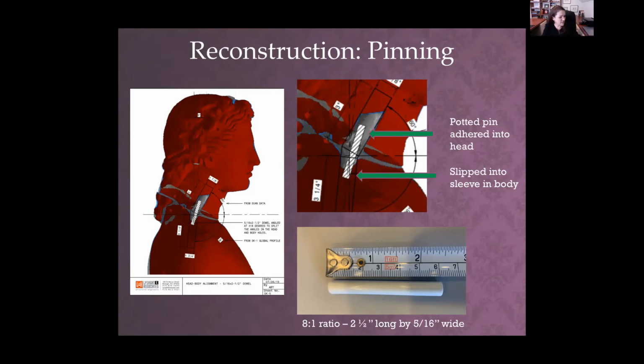One of the steps that we did say that we would use is that we ended up using a potted pin. The term potted pin in conservation means that the pin is adhered into one side of the joint. So we adhered it into the head, where we also created a sleeve in the body. So we cast a sleeve that fit the pin specifically into the neck, so that when the head fit on in the correct orientation, the pin would hold it in the right manner. And this would make it more easily reversible in the future.